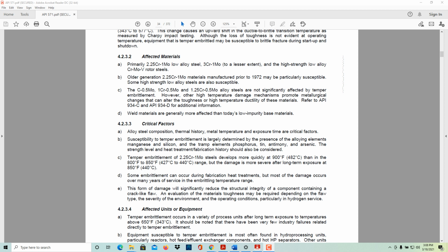Older generation 2.25 chrome 1 moly materials manufactured prior to 1972 may be particularly susceptible. Some high-strength low alloy steels are also susceptible. The 1.25 chrome half moly, 1 chrome half moly, and carbon half moly alloy steels are not significantly affected by temper embrittlement.